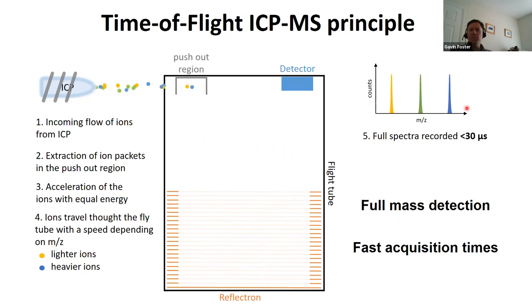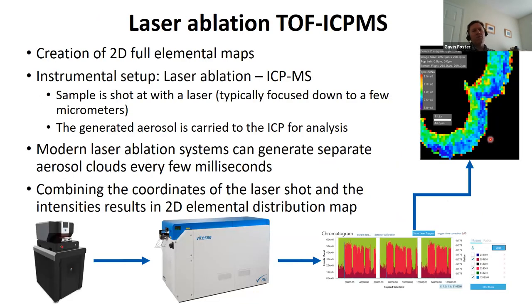And we've seen a few spectra that look like this already. And you get a full mass spectrum in under 30 microseconds. So like Amy, we coupled our Vitesse TOF to a laser ablation system to create 2D elemental maps. Amy already gave a nice introduction to laser ablation. So very briefly, we shoot the sample with the laser. The laser's focused down to a couple of microns, and that generates an aerosol that gets carried into the ICP for analysis. We get a cloud of aerosol generated every few milliseconds.